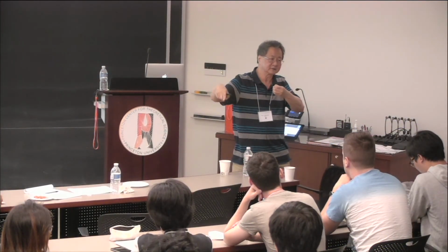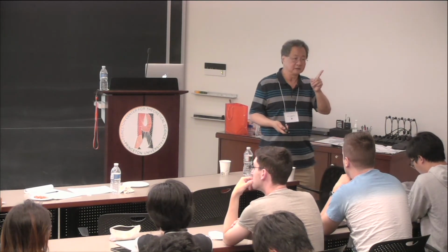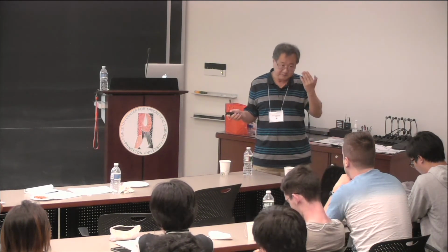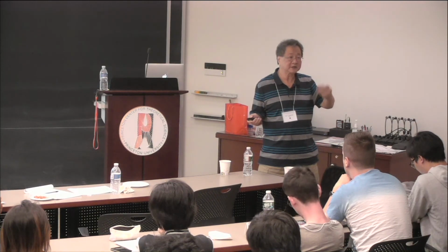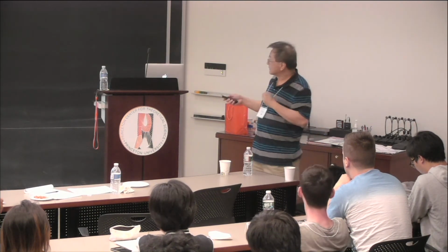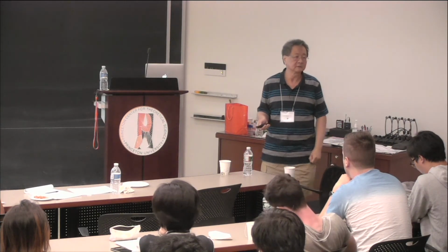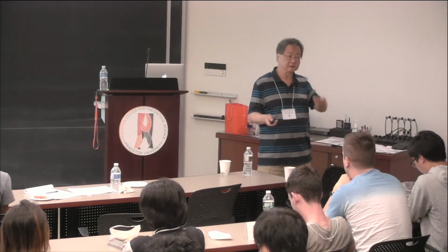Yeah, it's the same point as I was just mentioning, right? If you inject current, then the current is going to be carried mostly by the bulk supercurrent. But some of it is also going to be carried by the edge, a very tiny fraction. And the current will kill the bulk, not the edge. If you keep increasing the current in a magnetic field, that means you're moving in this direction. Then the bulk is going to be decreasing in its Ginzburg-Landau amplitude much faster, right? But the edge is immune to magnetic field. So an increasing fraction is carried by the edge current. That's why you start picking up this scallop profile. We view the conductivity measurement as simply a probe of the edge current.